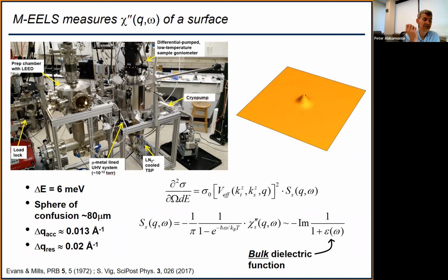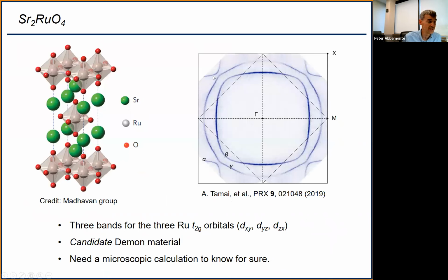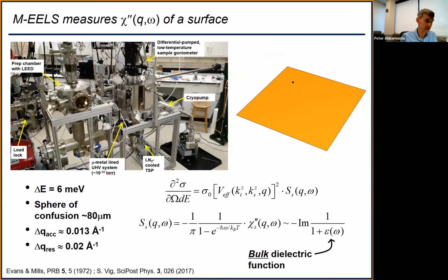There's a surface state, and the way you get rid of it is by exposing the surface to carbon monoxide. This was in a paper by the St Andrews group. Actually, this is the paper here. If you take the surface, cleave it in UHV and expose it to CO, then you get Fermi surface bands that look like this, and you really get bulk measurements out of a surface technique. But it's important to do that properly, and that's all that's in our paper. It's an excellent question. You have to get rid of that surface state to really get to what the properties of the bulk are doing. And that's true whether you're doing photoemission or STM or EELS or anything.